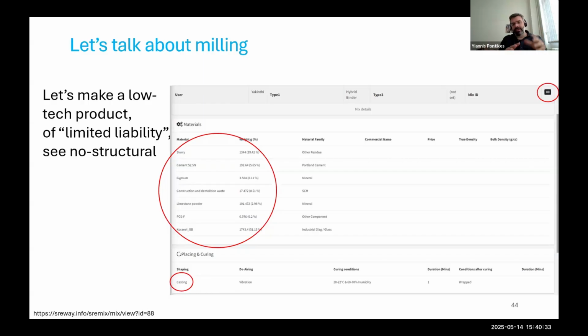And that's what we did. And then we also twisted the process a bit, and we said, okay, let's also add a bit of alkalis, a tiny bit. So not only do we have milling, but at the same time we also have activation. So you basically have dissolution while you do the milling. And then this is a database we created, so you can also access it. We also put things up on the web for people to see and duplicate or inform themselves.